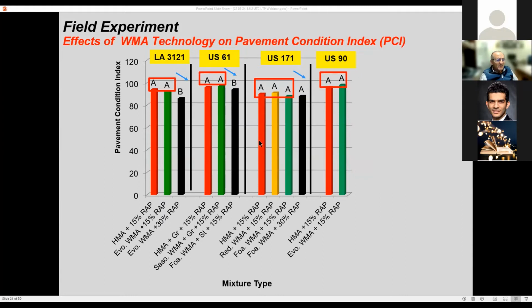Now, having said all these things, it's time to combine them all together. See, how do these compare? That's looking at a PCI. And looking at the PCI, what one observes in these combinations is that typically the WMA mixtures did at least as good as their counterpart HMA or slightly better. In some cases, this particular mixture that has a 30% RAP did show a lower PCI as compared to these other mixtures, based on these other distresses that were compiled in earlier measurements.